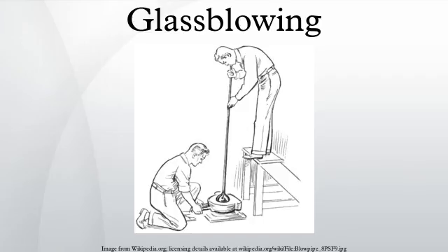In order to increase the stiffness of the molten glass, which in turn facilitates the process of blowing, there was a subtle change in the composition of glass. With reference to their studies of the ancient glass assemblages from Sepphoris of Israel, Fischer and McCray postulated that the concentration of natron, which acts as flux in glass, is slightly lower in blown vessels than in those manufactured by casting. A lower concentration of natron would have allowed the glass to be stiffer for blowing.